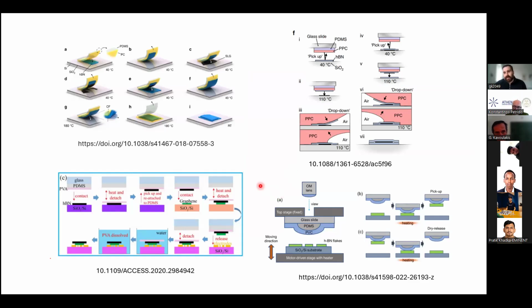Every other week, there is a new publication that demonstrates an iteration of these techniques, a new approach. All of them have their merits and their drawbacks. Most of them are based on using polymer films, like you see here, a PDMS film in combination with a PC film. PC film has high adhesion; it can pick up everything. It's very robust in this way, but there is an issue with PC. First of all, in order to put everything down, you need high temperatures, which again can relax the twist angle, and you might lose the moiré periodicity. And on top of that, you need to dissolve it with chloroform. And if you use chloroform for cleaning, you might also introduce new contamination to your heterostructure.